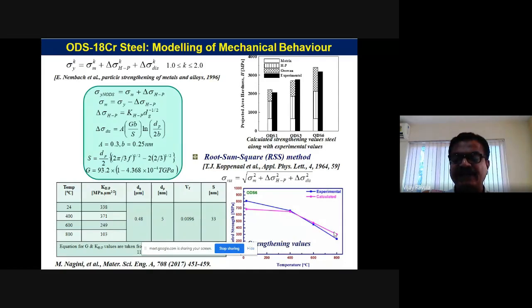And we were able to predict what my grain size and what my dispersoid size should be, so that I get a certain strength. The beauty is, two strengthening mechanisms are occurring here. One is grain size strengthening, and the other is dispersion strengthening. So generally, we can always have a nano-grained structure by working the material, either by rolling or equal channel processing. So you work on it, you roll it, and then you refine the grains.